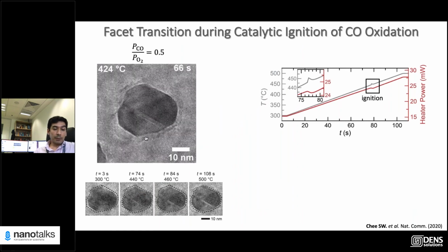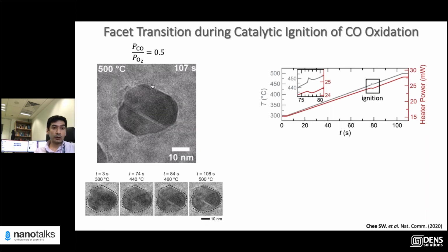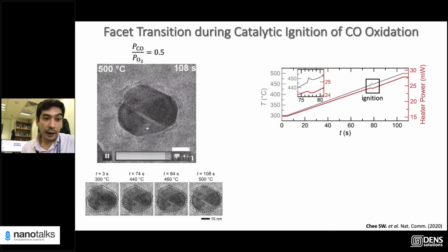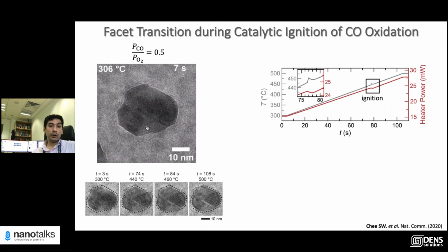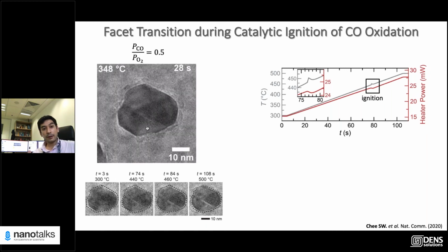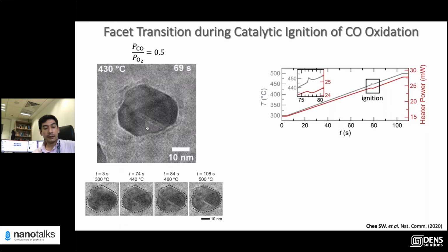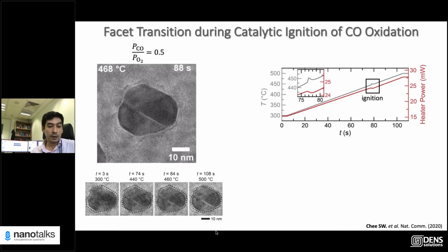So we are ramping up temperature from inactive to active. And you see, once you reach 450, so it's faceted originally, as your temperature hits right about 450 or so, the nanoparticle becomes rounded. And this 450 corresponds to the point where it transitions from a catalytically inactive to an active state.